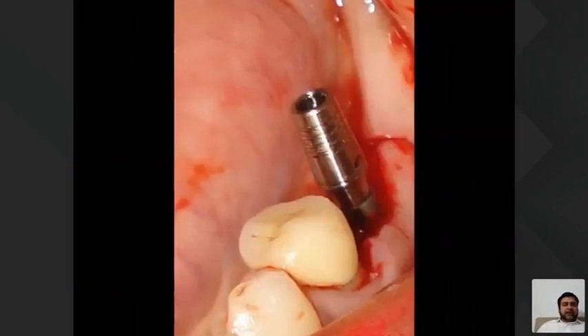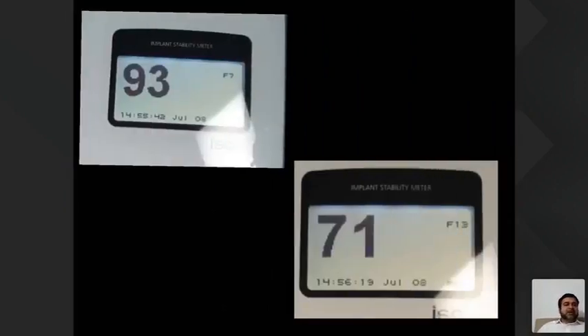Our implant in place after osteotomy was performed. So we took the ISQ value. It was one of the parameters to be evaluated. We had good ISQ values of initial stability of 93 and 71 in 2 different planes.